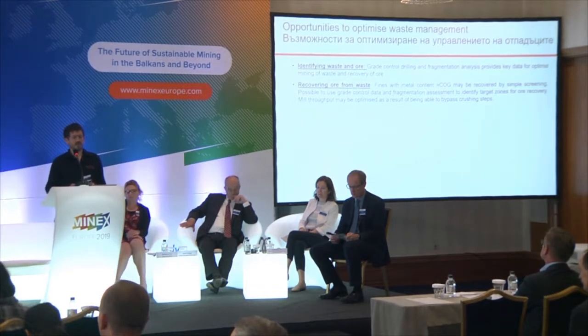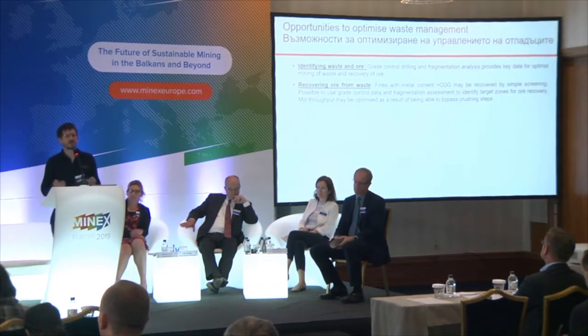Recovering ore from waste, it's very feasible to recover fines. Screening technology is well established. Installing a screening plant doesn't incur high cost. Dry screening is actually a fairly low cost solution. And the other thing is, if you're screening off the fines, you can bypass primary and secondary crusher and send this stuff straight to the mill.